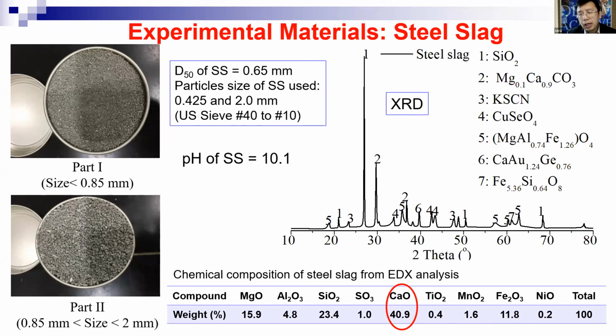And you can see here the calcium oxide is almost 41% by weight. The XRD also showed what the chemical composition in the steel slag is, and the pH of this steel slag is about 10.1. So this is the material here.